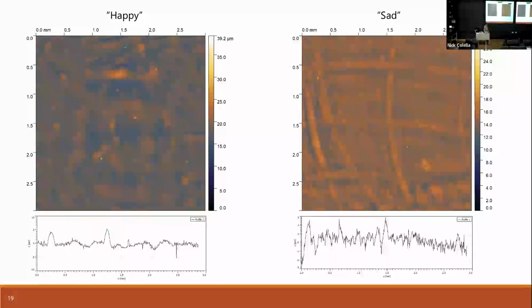And this is the data that we end up getting for the happy ball and the sad ball after removing the curvature. So we see some different functionality there, some different types of topography. In particular, for the happy ball, we see it's mostly flat with a few large bumps, whereas for the sad ball, we see kind of consistent noise and we see some kind of fibers or fibrils, something along those lines, across the whole surface. So very different topography.